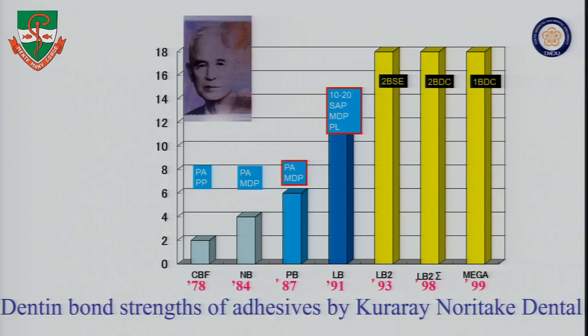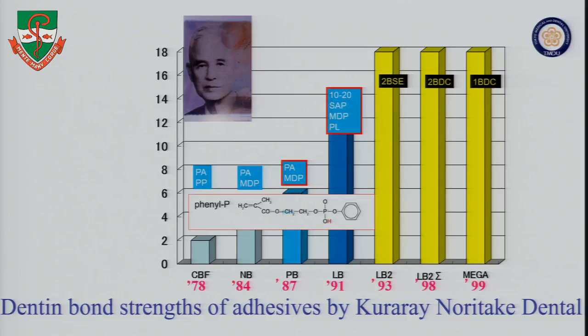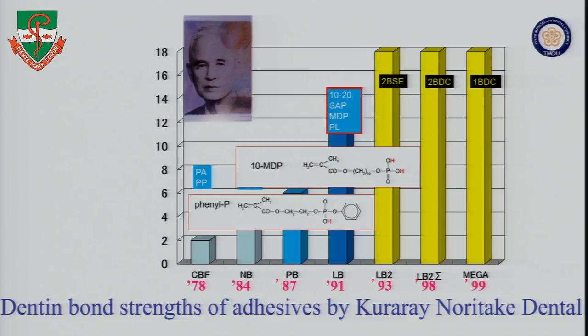In my department, we could accumulate the results of the bond tests, mainly of the products by Kuraray Noritake company, from the 1970s up to now. But at first, for the first material, the bond strength to dentin was very low compared to the recent materials. However, in the 1970s, we didn't have a good adhesive resin material. It was one of the best materials. And when the adhesive resin monomer was changed from Phenyl-P to MDP, the bond strength became two times higher. This is Phenyl-P and MDP. Now this 10-MDP is recognized as the best adhesive resin monomer in the world.